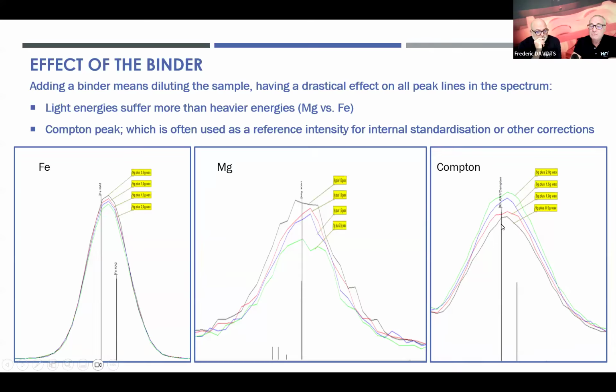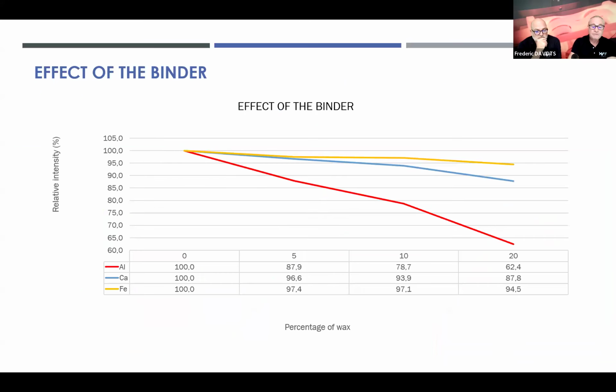And another one I could not leave out, because people analyzing geological samples may know that the Compton peak is very often used for correction, maybe an internal correction or just simply for a matrix correction. And also the Compton peak is, of course, being influenced by this binder effect. So, and here we can clearly see what is now the influence on the intensity.